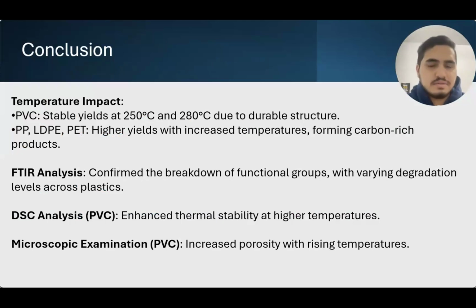In the results, we saw that PVC had a stable yield at both 250 and 280 degrees Celsius, likely due to its very strong structure even after hydrogenation and dechlorination. For PP, LDPE, and PET, we saw an increase in yield at the higher temperature. From the FTIR analysis, we showed the breakdown of the functional groups: PVC had minimal changes, while PP and the other plastics showed significant degradation.